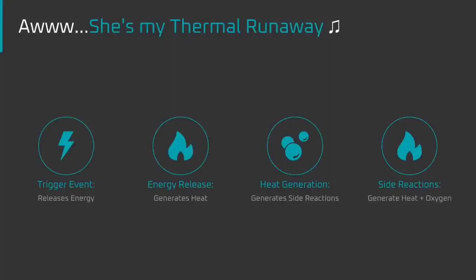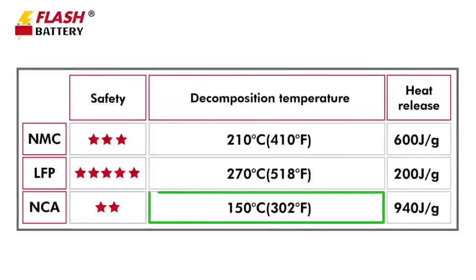When a battery cell shorts out, all of the energy in the cell is released in a matter of seconds, generating heat. That heat drives side reactions that release oxygen, generating more heat, which drives more side reactions. This loop is called thermal runaway. NCA starts decomposing and releasing oxygen gas at around 150 Celsius. When it decomposes, it releases heat on the order of 940 joules per gram. The end result is an explosive reaction that culminates in a molten fireball.